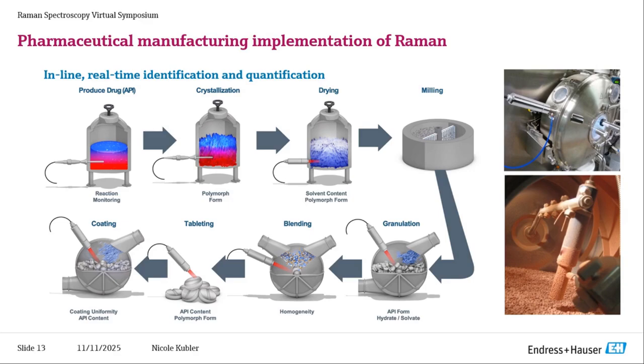Moving into crystallization, or your polymorph forms, Raman can identify polymorphic forms, so those different crystal structures of the same compound, which is critical as the polymorphs can affect solubility, stability, and bioavailability. In the drying stages, Raman measures residual solvent levels and confirms polymorph integrity during drying. With this, you can prevent incomplete drying or unwanted polymorphic transitions.